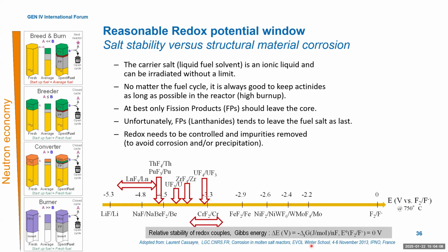And you need to control the salt. You need to control the redox. You need to remove impurities so that you are in the safe redox potential window. So if you were on the oxidative part, the corrosion or oxidation of the structural material can be quite strong. If you are on the reductive part, you may have an issue of precipitation of actinides and other elements. So according to your system, your structural material, the salt and fuel cycle you select, you need to find your redox potential window for operation. If you control this redox, and if you keep the salt clean, there are not necessarily big issues with corrosion.